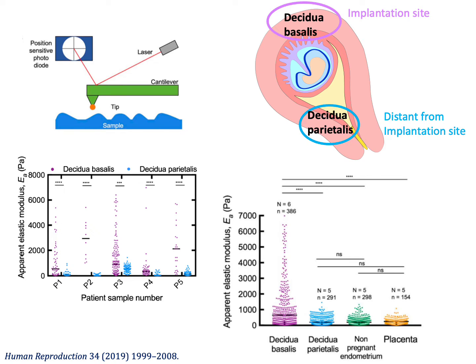What we've done here is looked at the mechanical properties, as measured with an atomic force microscope indentation test, comparing in a series of individual patients the decidua basalis and the decidua parietalis. As you can see, both in the graph on the left for the individual patients and the graph on the right for the combined data, there are significantly stiffer regions of the decidua basalis at the implantation site compared to the parietalis, and the parietalis is actually comparable to both the non-pregnant endometrium and to the placental tissue at third trimester.